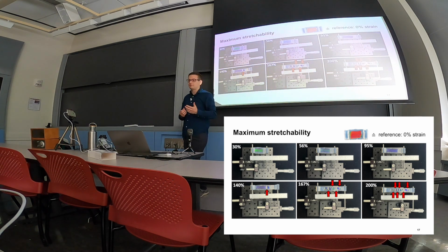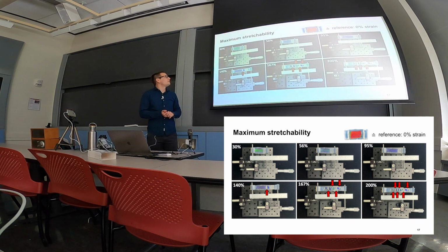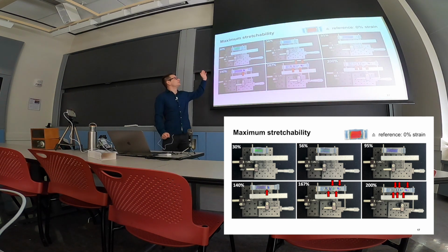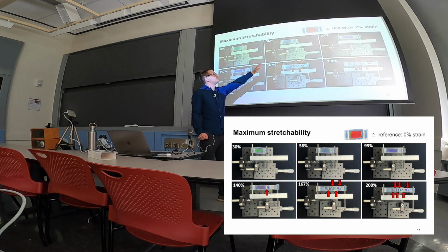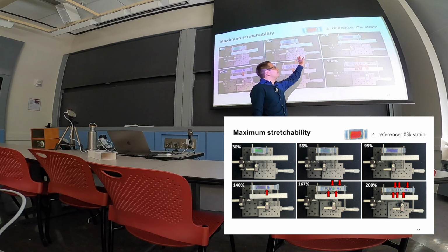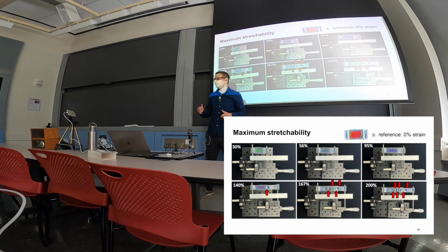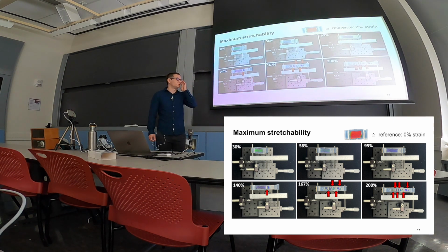And then for the maximum stretchability, we see a reference sample over here on the top right with 0% strain, so still being in a red color with the peak wavelengths. And then I just wanted to see how far I could stretch it without it being destroyed. So we see for 30, 56, or 95% of stretching, we shift through the whole spectrum, but there's no destruction that we can see. However, we should not stretch it more than 100%, because after that we shift into UV, so we cannot use the sensor anymore, especially not when we want to use a camera system for analyzing that.